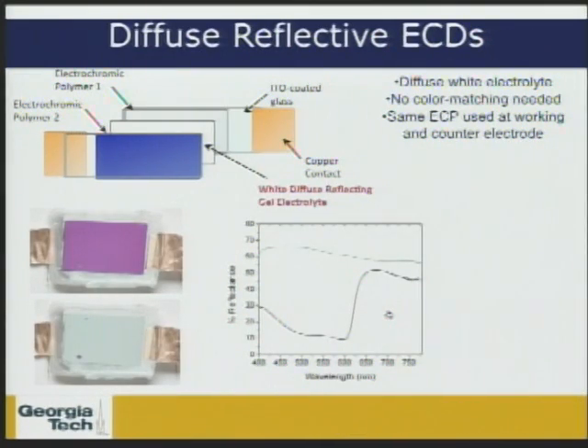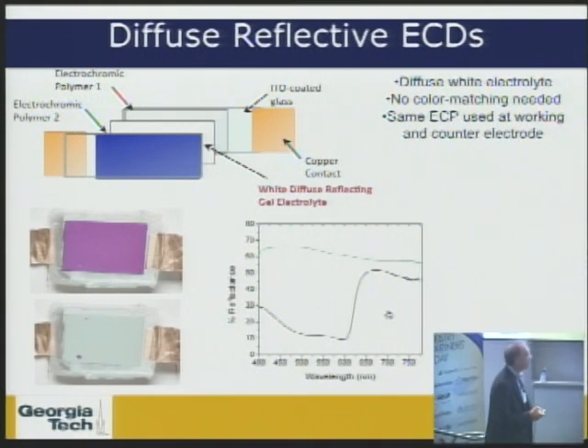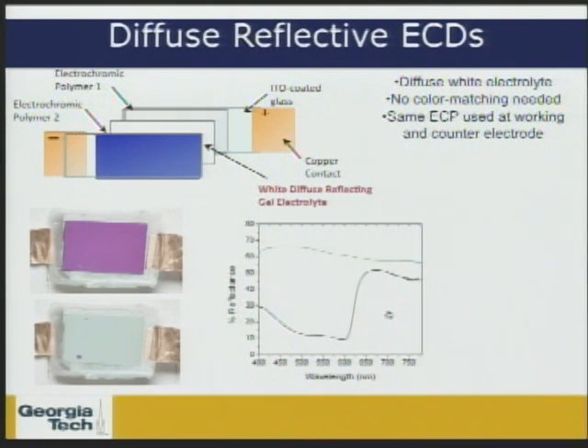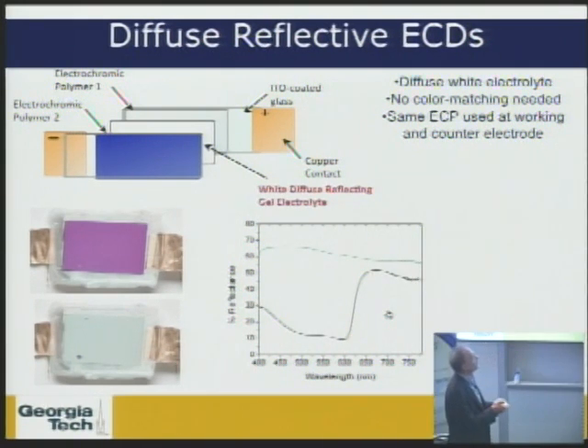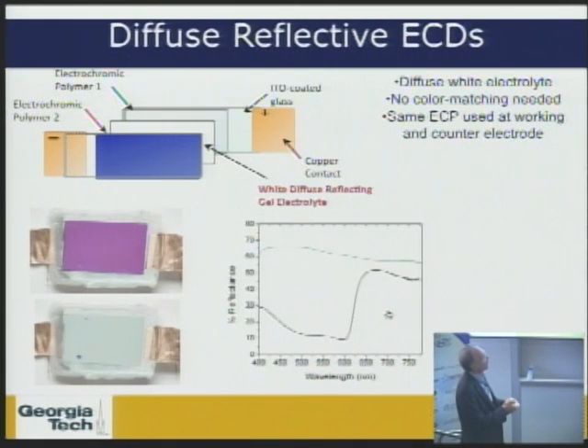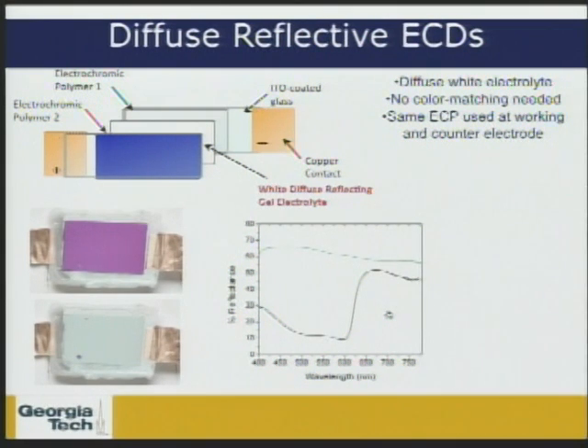Now, let me just show you how we can apply this in a small device type. What you're looking at here is an ITO glass with a coating of our polymer on there, and another ITO glass with the same on the back. If we put an electrolyte in the middle, and we, in essence, imbibe this electrolyte with titania, then we have a white reflecting inner layer. We can then set this, as we did with the capacitors, one neutral, one oxidized, and so the polymer in the front will be colored, the polymer in the back will then be in its transmissive form. When we change the bias on that cell, that front polymer will go into its transmissive state while the back polymer goes into its colored state.